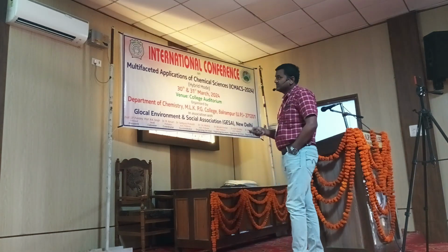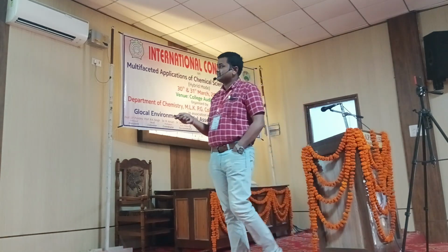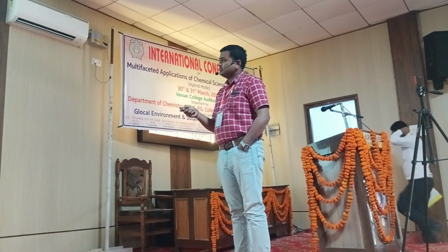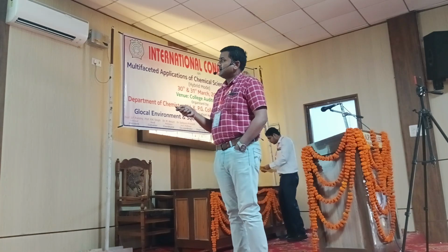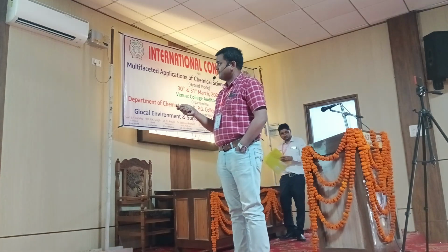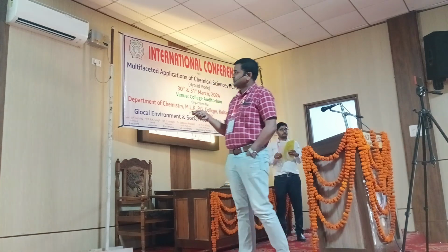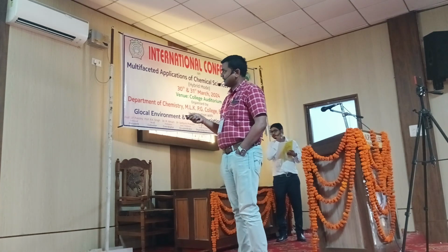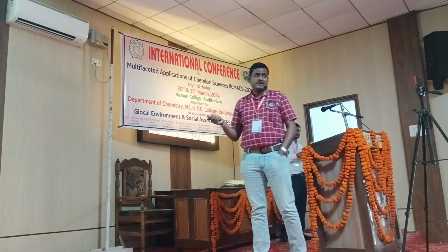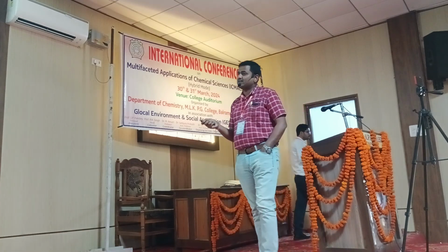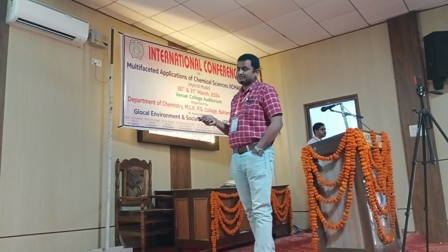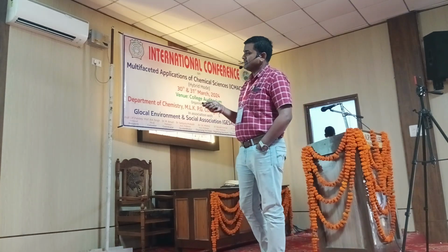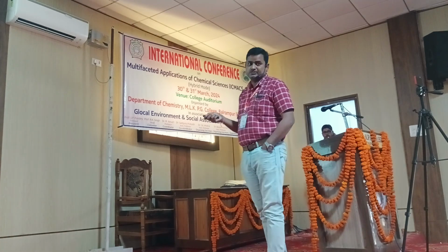Next, this is the possible mechanism of J aggregation. This is the schematic representation of graphene sheets functionalized with ammonium cations, and these ammonium cations have a tendency to form electrostatic interaction with carboxylate ions and hydrogen bonds. These two phenomena suggest J aggregate formation, because J aggregate formation only happens when the molecule has electrostatic and hydrogen bonding interactions.